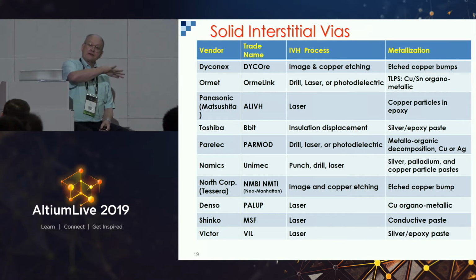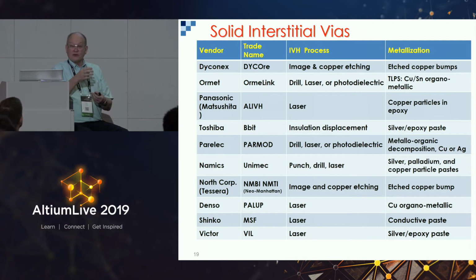And you screen print it like you would a solder paste for assembly, but you're screen printing it into a via hole that's either drilled or laser drilled. And you screen print it until it's all filled up, usually with a vacuum chuck so there's no air. Then you dry it, and then you sinter it. And at the sintering temperature, the binder is driven off, the liquid melts, they connect to the lands and the other things, and they form a solid metal via.